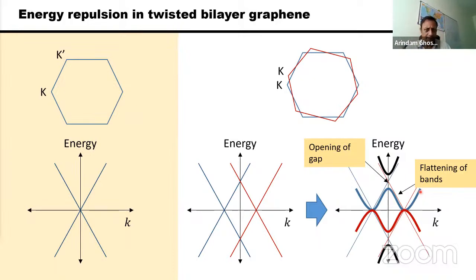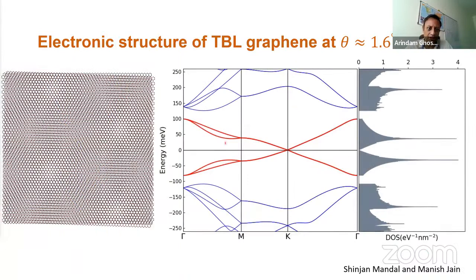There is one more interesting aspect that one needs to talk about, that is the density of states. See, when you have these flat bands, you have the density of states which is zero at the edge of the bands, and this is called a moiré gap. But at the center of the band, because of these flat regions, there is a very large density of states, and these are called van Hove singularities. Okay, this one and this one. So most of our experiments that we do in the lab are confined to this low energy moiré band. We usually don't go to much higher energy, but mostly confine ourselves to these low energy moiré bands and change our electron density or Fermi energy between these bands using electrostatic means.